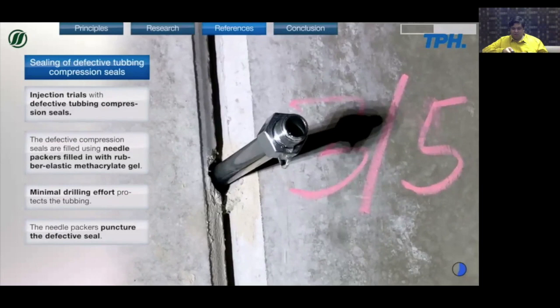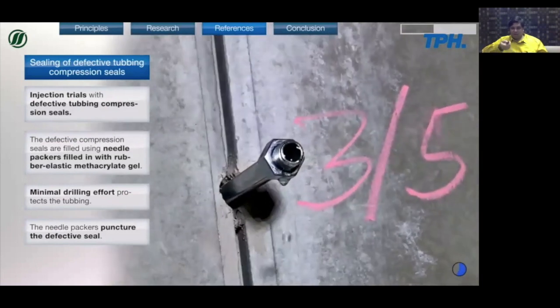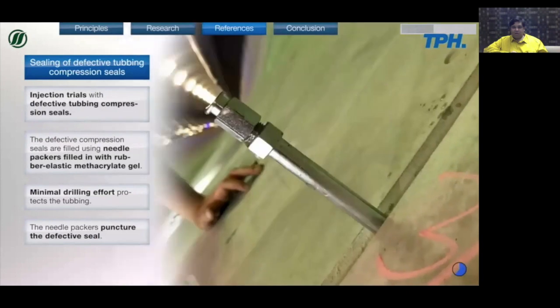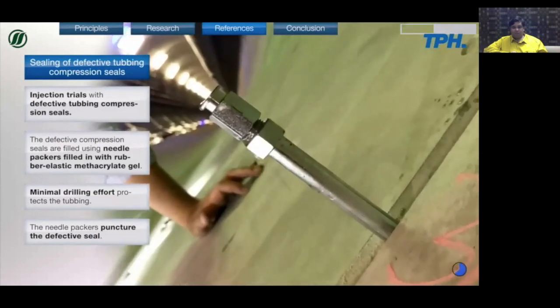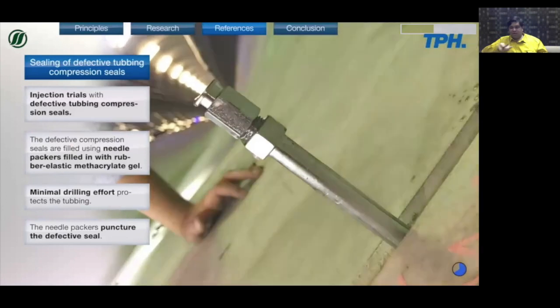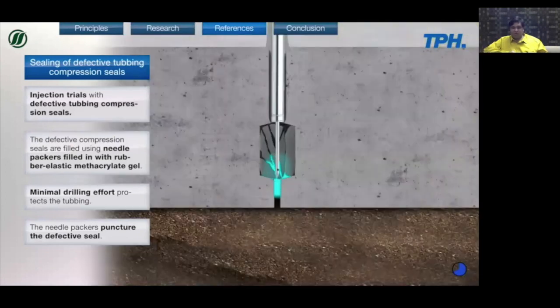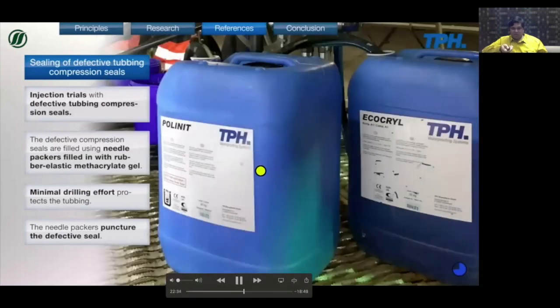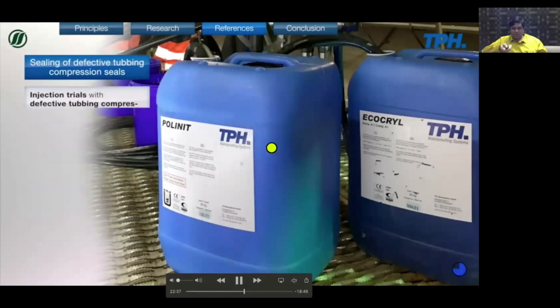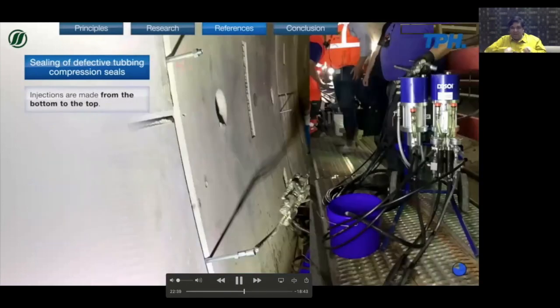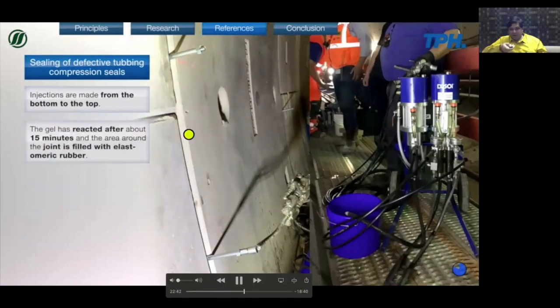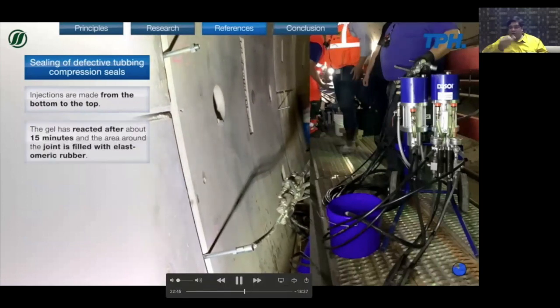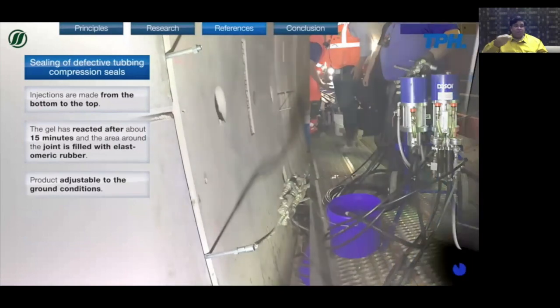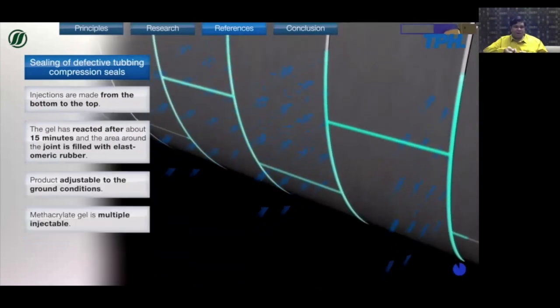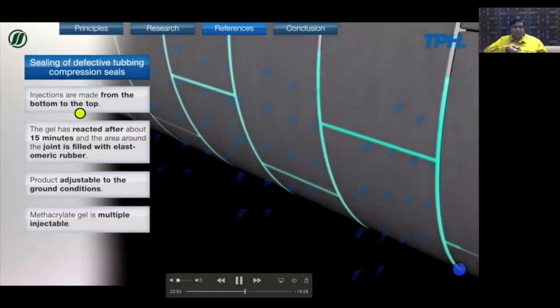So here you can see they put in the needle packer, a packer to help inject the material. You can see the water coming in, and once this part is injected, it fills up both whatever is damaged in the gasket itself, sealing that, as well as the area behind the joint. So at any point in time, if there is further water ingress trying to come in, that doesn't happen. And it is pretty quick because the gel reacts in about 15 to 20 minutes.